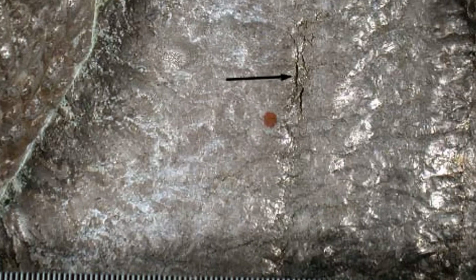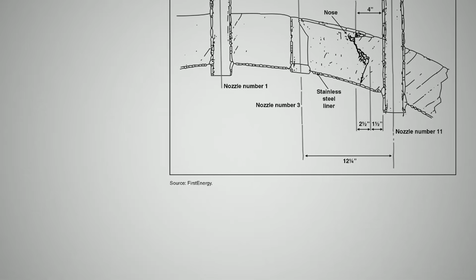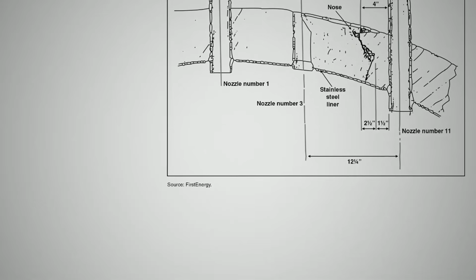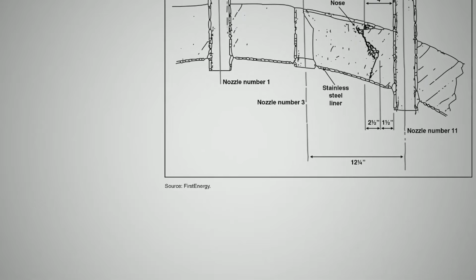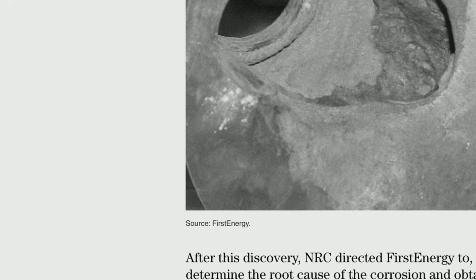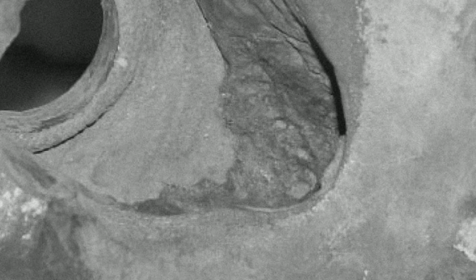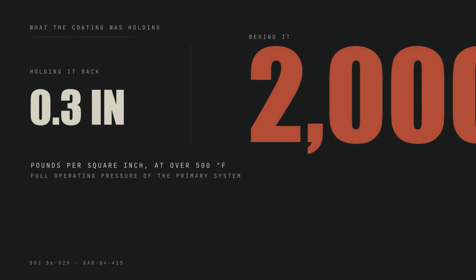And then the corrosion stops. It stops because it hits the stainless steel cladding, the raincoat on the inside face. Stainless is far more resistant to boric acid attack. The chemistry that ate 6.5 inches of carbon steel could not get through a layer a fraction of that thickness, which sets up the exact situation in the photograph. The strong material is gone. The weak-looking material is holding. And what it is holding back is the full operating pressure of the primary system, about 2,000 pounds per square inch at over 500 degrees Fahrenheit.